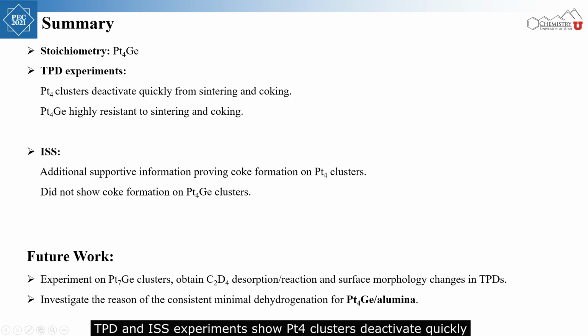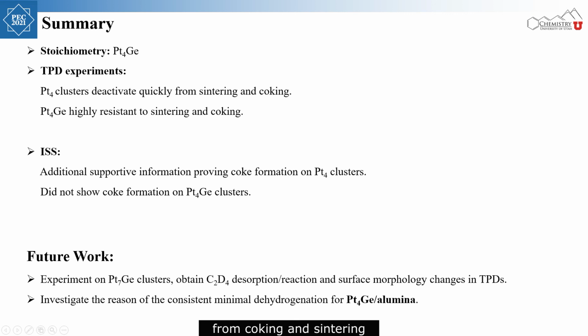TPD and ISS experiments show that platinum-4 clusters deactivate quickly from coking and sintering, while platinum-4 germanium clusters are highly resistant to coking and sintering.